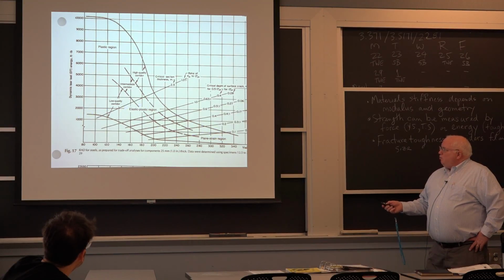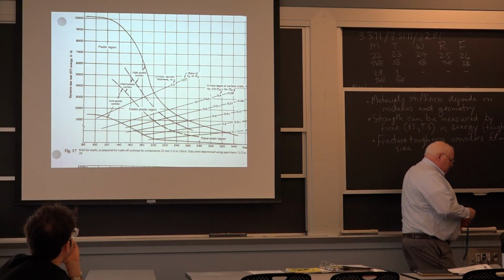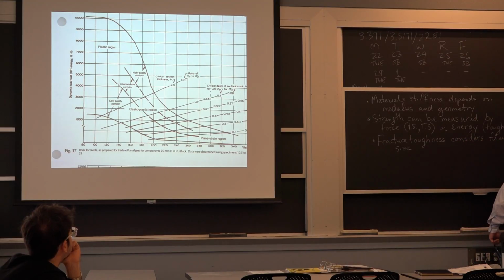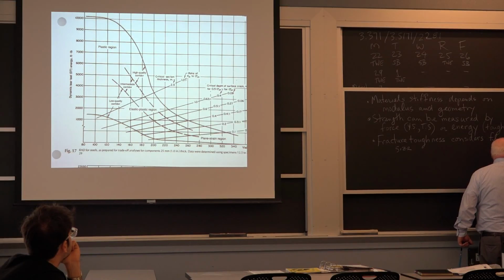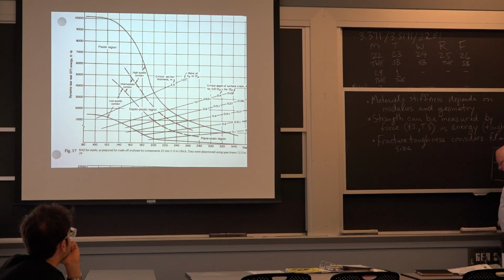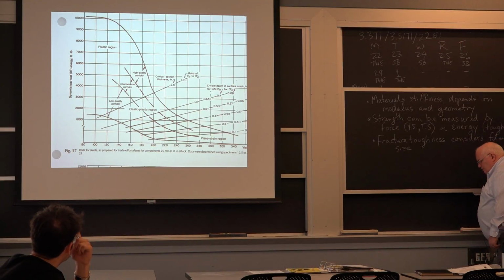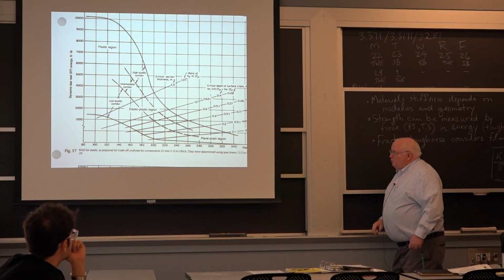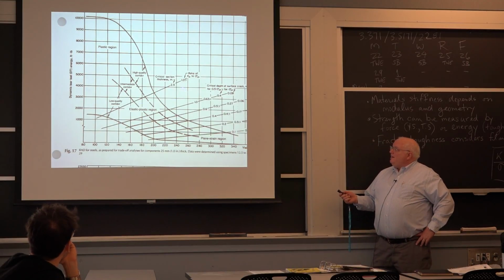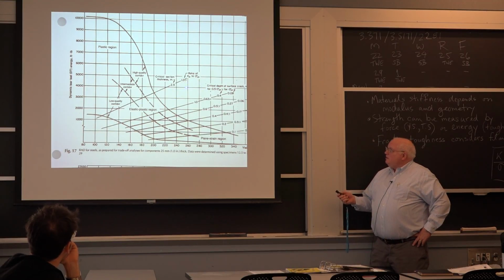And on this thing, you can plot the size of the flaw. The reason he called it a ratio analysis, if you take this and bring it down underneath, K over sigma must be greater than the square root of pi c. So he's looking at the ratio of the toughness to the strength, energy of fracture to force of fracture at the yield strength of the material. And from that, he can calculate a critical flaw size. And this is the critical flaw size line right up here for 2.5 inches.